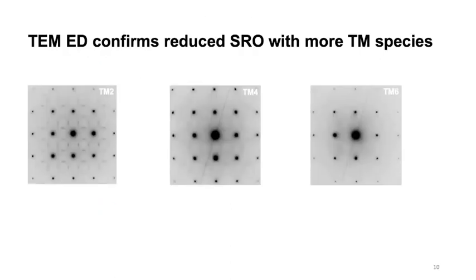To characterize the short-range order in those three materials, we took electron diffraction of the synthesized material. As we can see in those electron diffraction patterns, the round spots represent the long-range ordering, and we can see that TM2, TM4, and TM6 all show the same long-range ordering, while this square-like diffuse pattern represents the short-range order feature.